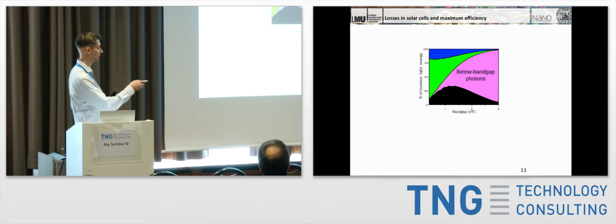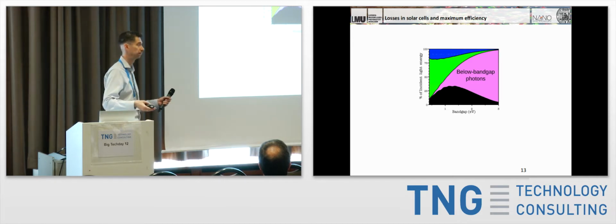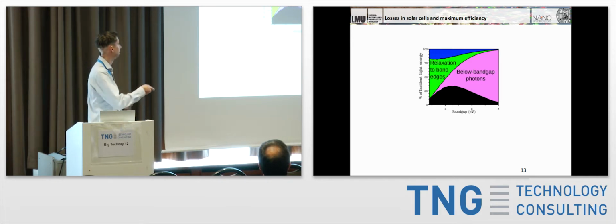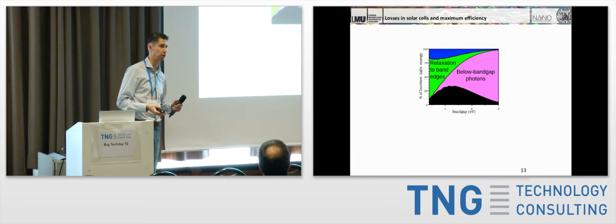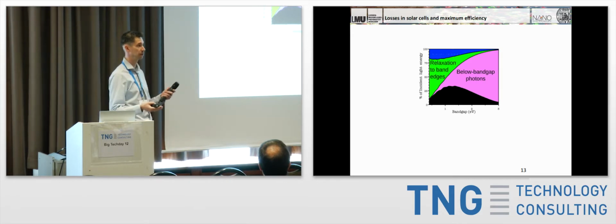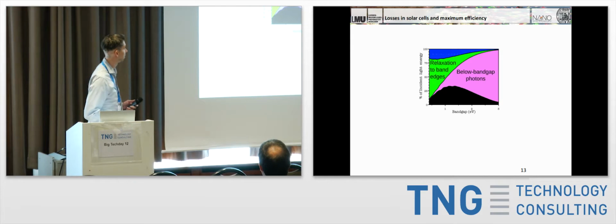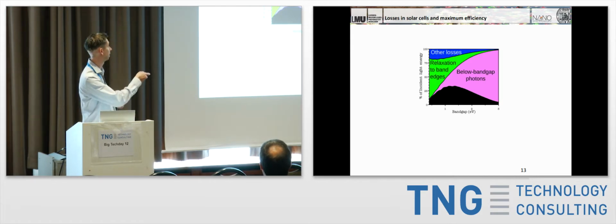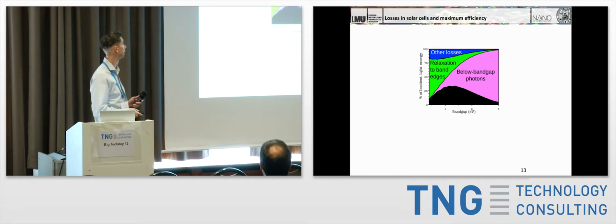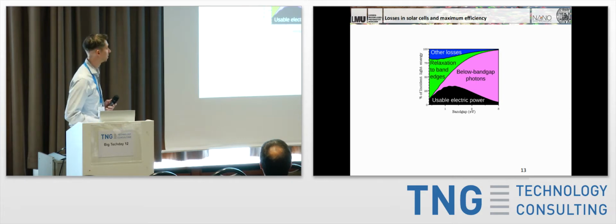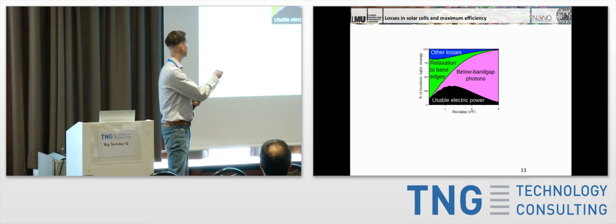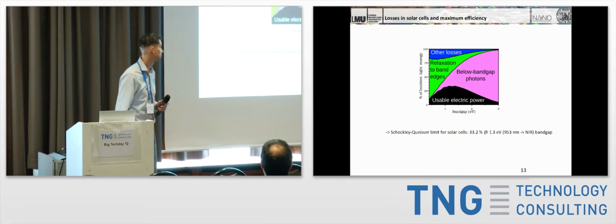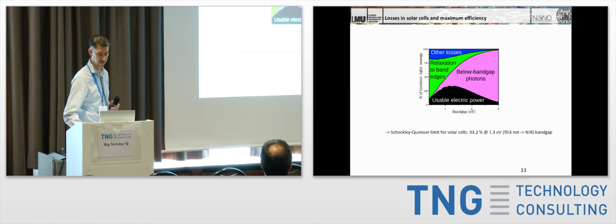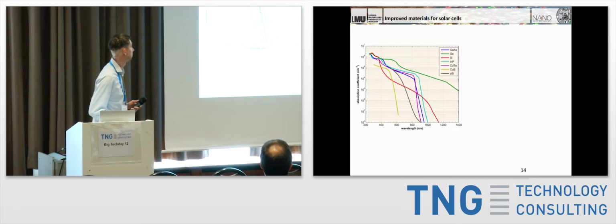And if you look at the different regimes, as you're increasing the band gap energy, more and more of these photons can't be absorbed, and so they're all going to be wasted. Any photon that has energy larger than the band gap essentially still only produces one electron-hole pair, and all the other energy above that is also wasted because the charge carriers just relax down to the band edges. So all of this area is already wasted then. And then we have top contact reflection, we have interface issues, and so those add up to the other losses. And so out of this entire square, this is the only usable electric power that you actually have from a single junction solar cell, which maximizes out to about 33% if you have an optimal band gap of about 1.3 electron volts, so about 900 nanometers, so also easily into the NIR, the near infrared region.